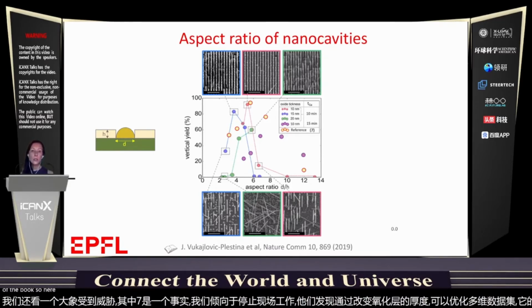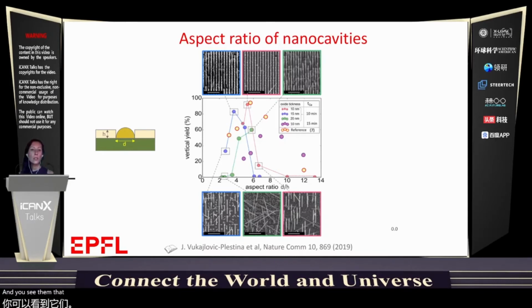So here we universalize this and show that this is the aspect ratio. And you see then that by using different thickness of oxides and different size holes, we can get to very high vertical yield. And this is what drives the very high yield. So you have here examples of very good yield of vertical growth. And this is absolutely reproducible when you prepare the substrate right.